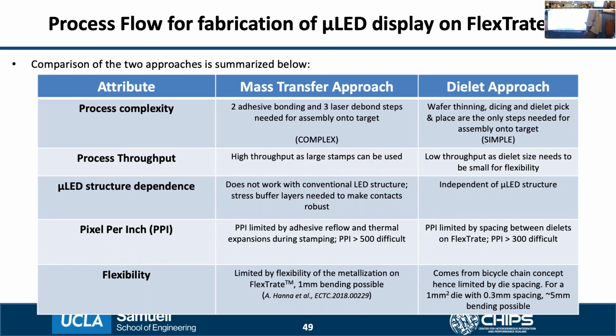In terms of process throughput, the mass transfer approach can reach very high throughputs because we can simply increase the size of the stamps used. The dielet approach, however, is typically low throughput because it is limited by the dielet size. We use 1 millimeter square dielets, and we cannot use smaller dielets because they are more difficult to handle. If you use larger dielets, it compromises the flexibility of the overall sample. Then, very important, is the micro LED structure dependence. What we found is that the mass transfer approach does not work with conventional LED structures because the contacts can delaminate during this process. We essentially need to make special LEDs with customized structures with stress buffer layers so that the contacts are well preserved.